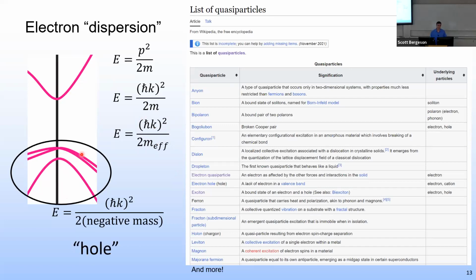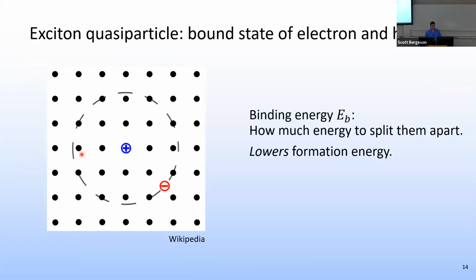There's another quasi-particle that I'll be talking about next, which is called the exciton. This is a bound state between an electron and a hole. A hole acts like a positive particle, the electron a negative particle, and so they're attracted to each other, and they can form bound states that are a lot like hydrogen atoms. And they can be described by the binding energy, which is how much energy it takes to split them apart. And because it takes energy to split them, when the exciton forms, it actually has a lower formation energy than just having the electron and hole separate from each other.